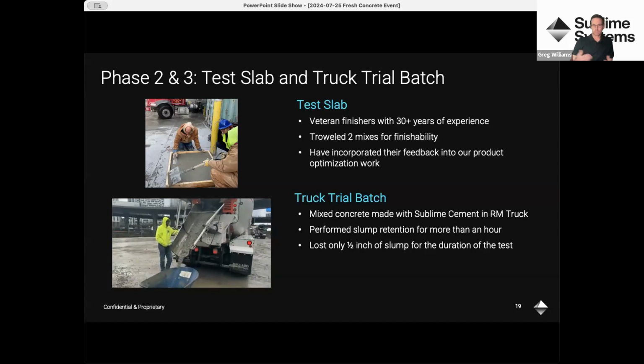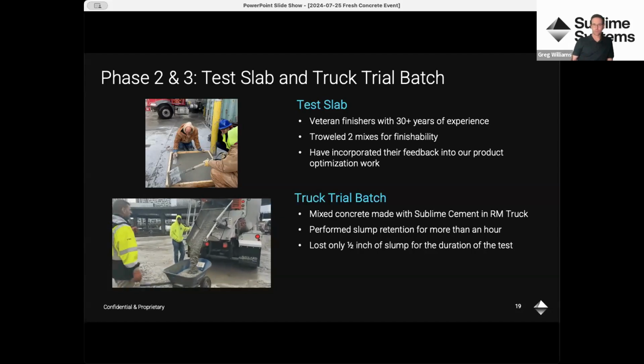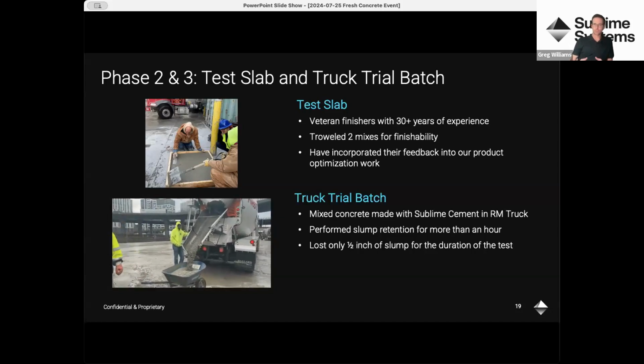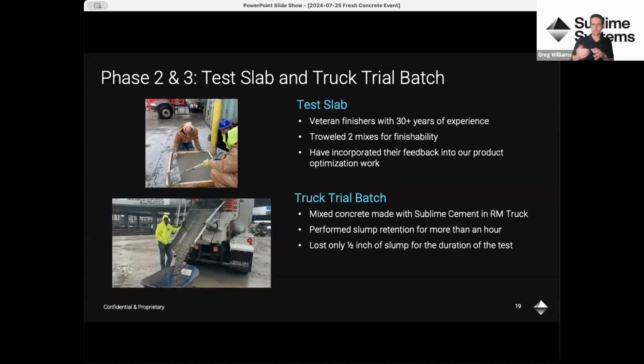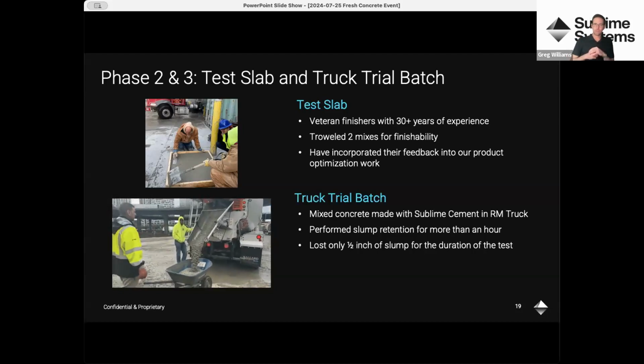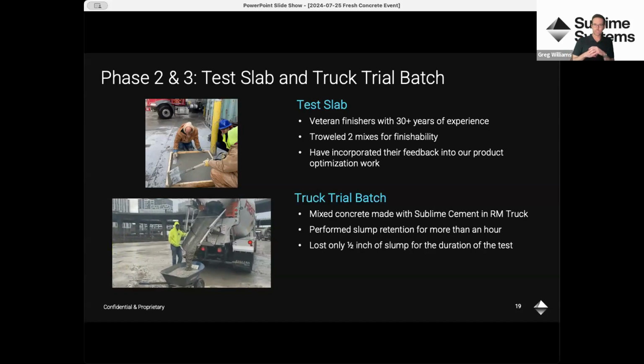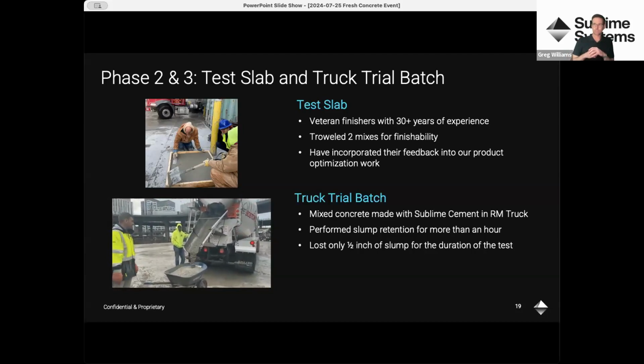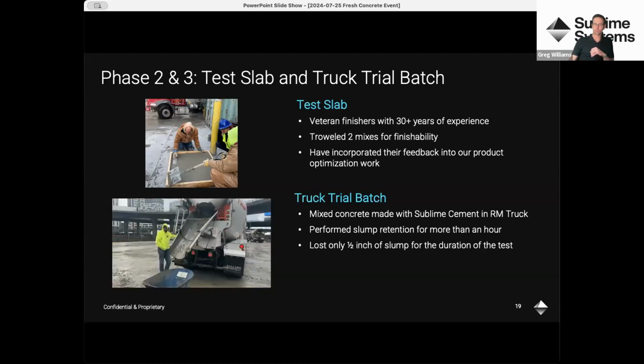We then batched some larger batches, did a truck trial batch to see how the material performs in a larger batch, how it retains slump when you are in transit to the job site to make sure it's still workable. And this basically showed that the material characteristics were consistent in larger quantities, and you could get to the job site with workable material.